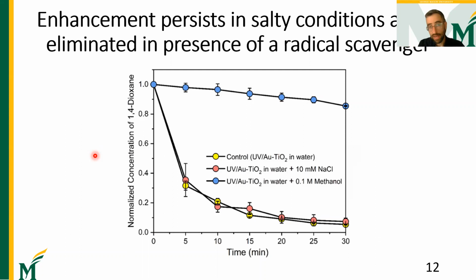Next, we looked at the effect of salt and of adding a radical scavenger, namely methanol. So first, if we add salt, and remember, this is enough salt that it should attenuate the self-propulsion entirely, the enhancement is virtually unchanged. So this was interesting because it suggests that self-propulsion, at least in this system, is not essential to observing the significantly enhanced degradation that we see. In fact, it likely doesn't play much of a role at all.